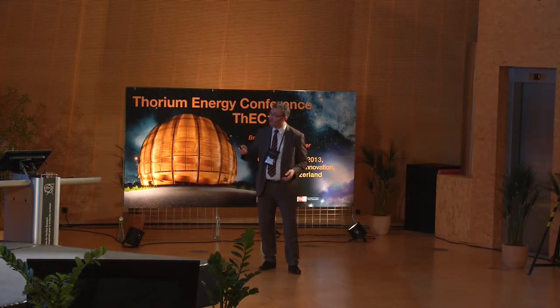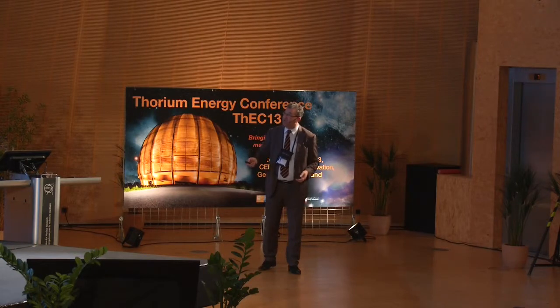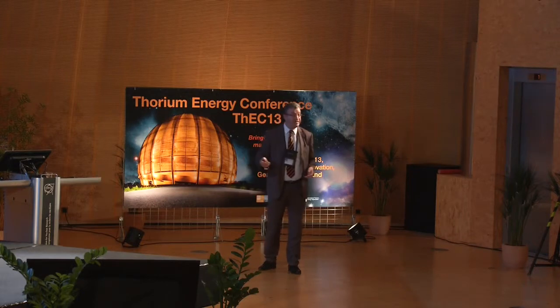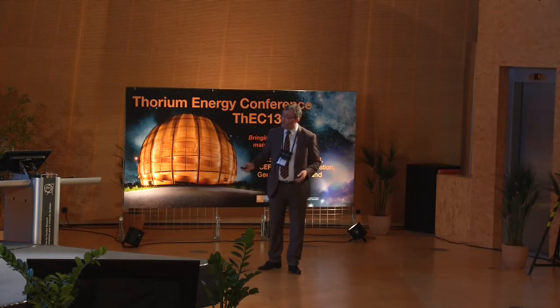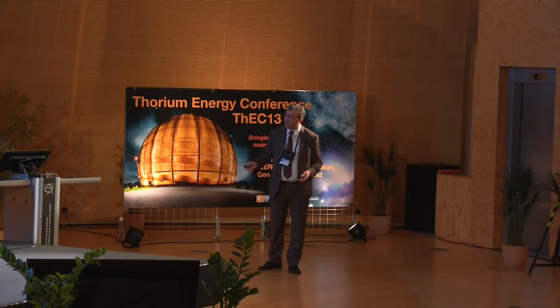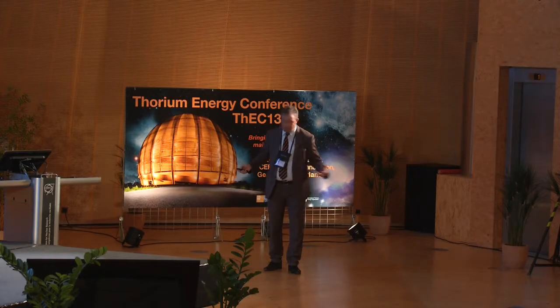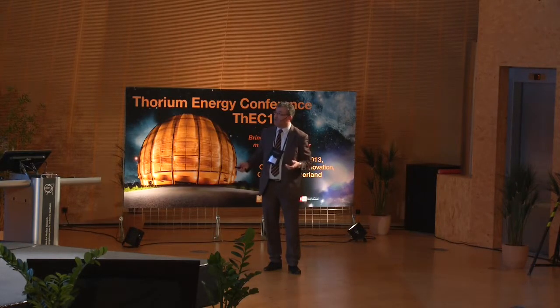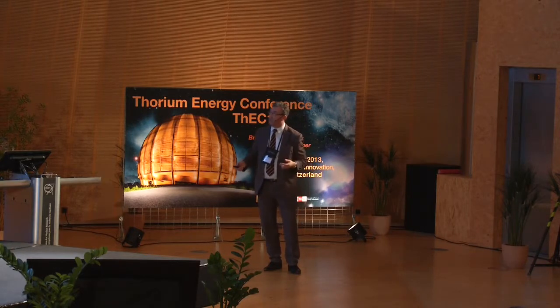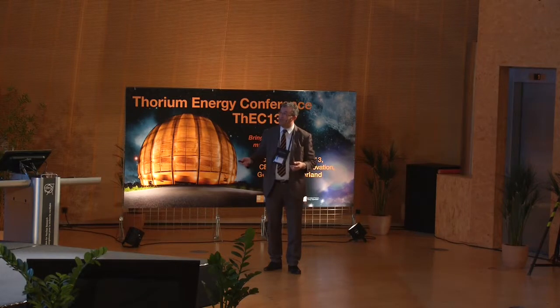I will just go very rapidly. I said this is a multi-purpose research facility. We can do irradiation of material in those positions I showed you, accessible from the lead. And you see the amount of dpa per year we can achieve, the level of flux, total flux we have in there. For material for fusion, we can even put in the flux of the spallation neutrons, under the spallation target, a special device that we have developed for hosting the material samples, and we can put them from underneath the same way we put the fuel assemblies or the control rods, whatever. And we can put them in a very controlled environment of temperature, and also a range of temperature can be defined.